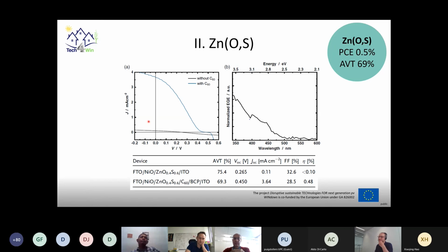So back to the JV results, with and without the C60. And with the C60, you see it's clearly improved, and we're getting a 0.5% efficiency for the moment. Having at the same moment an AVT of 69%, so above what we were aiming for. Still, there is room for improvement.